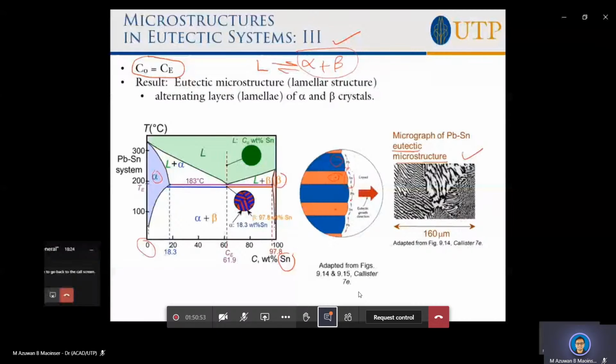Okay, so you have diffusion going on here, right? All the atoms of plumbum trying to move into the alpha layer, and then the stannum, tin, trying to move into the beta layer. So you can imagine they cannot run far. Therefore, they just run to the top layer, to the bottom layer. So that's why they grow into alternating layers. Okay, so they don't have to travel from bottom to up. So they just arrange themselves to be at the closest vicinity.